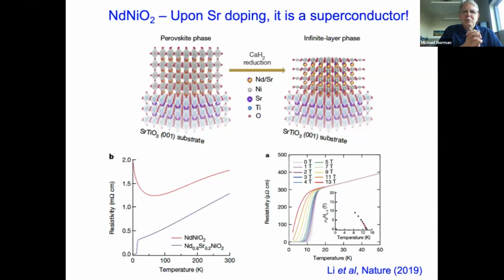And what, again, you do is this topotactic reduction. The nice thing about using films is that the substrate provides an orientation. The problem is the perovskite is cubic, and so when you reduce the bulk material, then you have c-axes pointing all over the place. Whereas if you grow on a film, then of course the substrate aligns the c-axis. And the net result is that you get much higher quality material if you do it in thin film form than if you use the bulk.